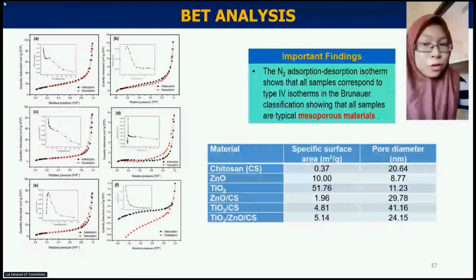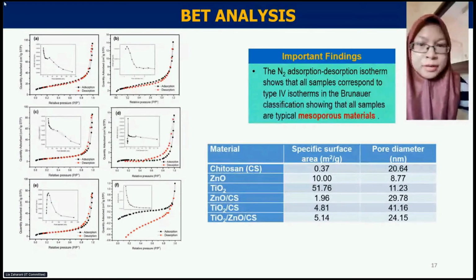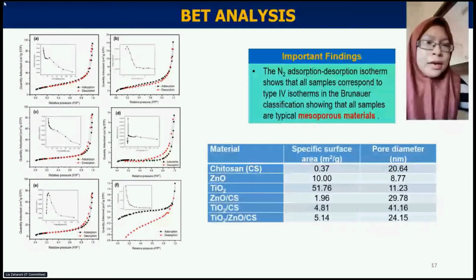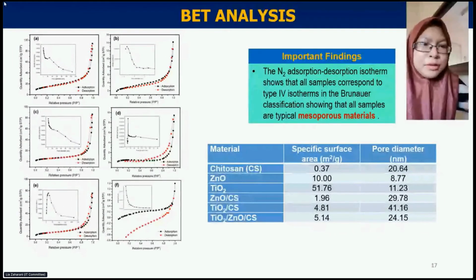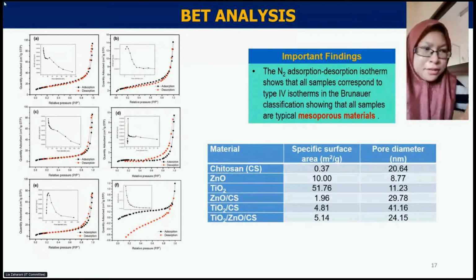In order to examine the pore structure nature of this hybrid system, the BET gas adsorption measurement has been carried out. The nitrogen adsorption-desorption isotherm curve of the hybrid system has also been calculated, showing that this type of hybrid system corresponds to the type 4 isotherm in the Brunauer classification, and showing that it's a typical mesoporous material.